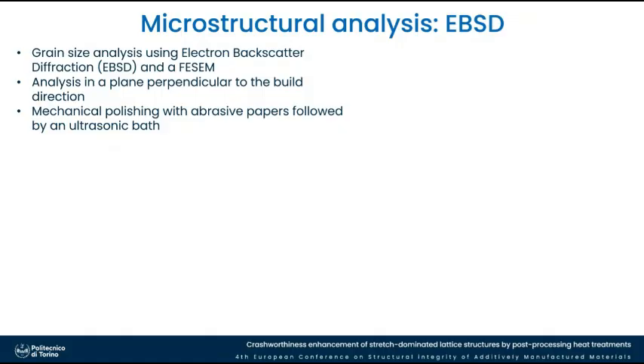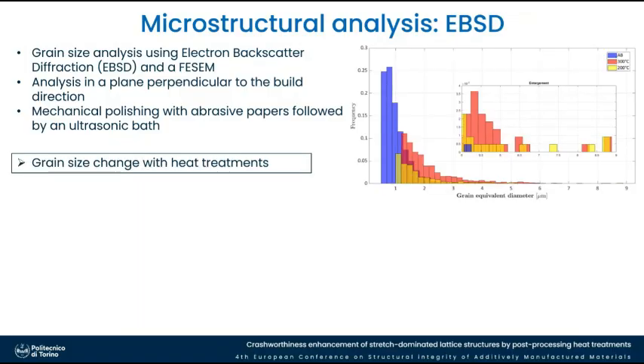Then moving to the grain size, we did an EBSD analysis in a plane that is perpendicular to the build direction. And what we observed was that the heat treatment affects the grain size, increasing it, basically. You see that in this figure on the right. So at 300 degrees, we have, on average, the biggest grain size.